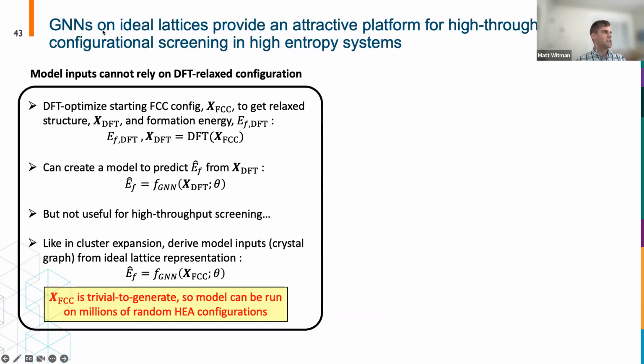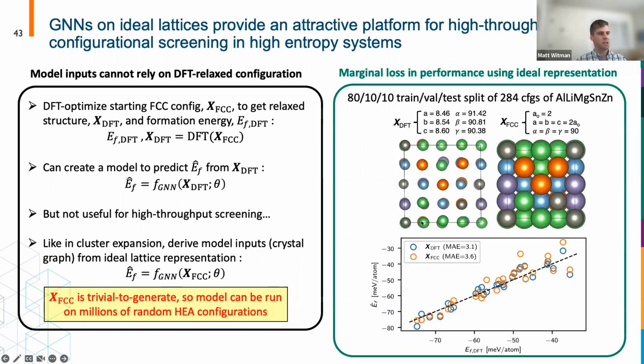So going back to GNNs now, these are an ideal situation for doing this configurational energy screening in high throughput. Typically we take a DFT structure and optimize an initial guess of the structure, let's say it's X FCC, to get the relaxed crystal structure X DFT and its formation enthalpy. Of course, you could create a model to predict the formation enthalpy using the DFT relaxed representation, but that's not useful for high throughput screening because you need to do the DFT relaxation to get the model inputs. So just like in methods like cluster expansion, we can derive the model inputs using graph neural networks, but with this idealized X FCC representation. Since it's trivial to generate, we can screen millions of configurations. You pretty much see no degradation in performance whether you use the relaxed DFT structure or this initial idealized X FCC representation. This is the test set predictions on the exact same configurations, and the error is pretty much negligible.